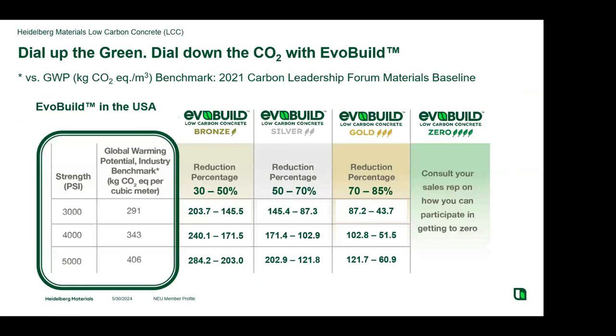So what those numbers mean when you start actually cranking the numbers and looking at the evaluation is pretty straightforward. We take the benchmark, which is listed here inside this box. You can see for a 3000 PSI mix, the benchmark GWP, or the benchmark embodied carbon for that mix, is 291. We reduce that by 30 to 50% to sell a bronze product. Therefore, our global warming potential for these mixes will have to be below 204 up to 145, right? 203.7 to 145.5, etc. So it's very straightforward. It's very beneficial. The neat thing about this is we can show it on our EPDs. You can see very clearly what the GWP associated with our mixes are, and you'll see just by the name of what we're selling you that material is going to be a low carbon concrete.